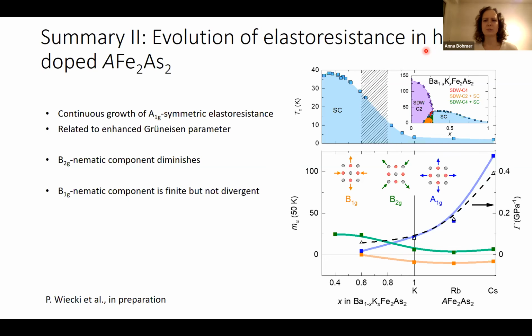Okay, I think there's two components. No, the theoretical modeling did not take that into account. When you talk about magnetic moments, I think the role of nickel in this 114 is just the same as nickel in the 122s, and that was studied quite in detail. It is an impurity. We see an enhanced residual resistance. We see enhanced scattering. Yeah, there's no moment on that. Exactly. There's no magnetic moments there. It's an impurity in the iron plane, so it's quite significant, but there are no extra magnetic moments. I see. Okay, thank you.